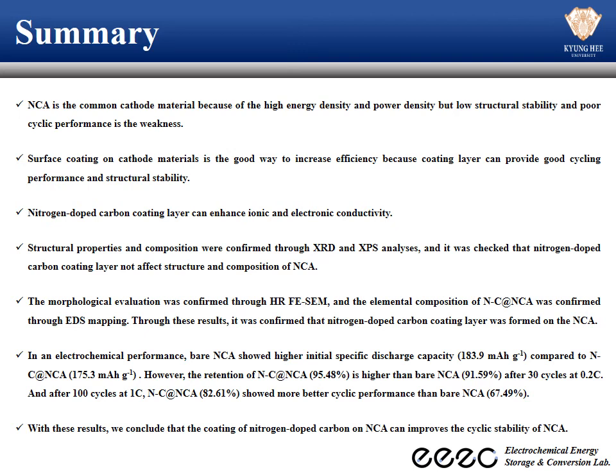So, to summarize what has been covered so far, first, NCA is a common cathode material because of its high energy density and power density, but low structural stability and poor cyclic performance are its weakness. So, surface coating on cathode material is a good way to increase efficiency because a coating layer can provide good cyclic performance and structural stability, and a nitrogen-doped carbon coating layer can enhance ionic and electronic conductivity. The structural properties and composition were confirmed through XRD and XPS analysis, and it was checked that the nitrogen-doped carbon coating layer does not affect the structure and composition of NCA. The morphological evaluation was confirmed through HR FE-SEM, and the elemental composition of N-C@NCA was confirmed through EDS mapping.